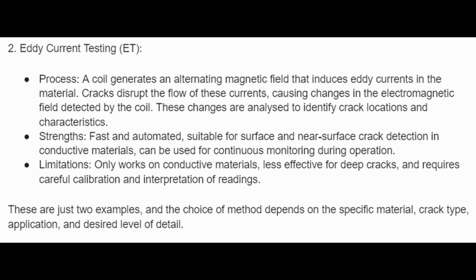Its strengths: it's fast and can be automated, suitable for surface and near-surface crack detection in conductive materials. It can be used for continuous monitoring during fabrication and manufacturing operations. Limitations: it only works on conductive materials. It's less effective on deep cracks and requires careful calibration and interpretation of readings. These are just 2 examples, and the choice of method depends on the specific material, crack type, application, and desired level of detail.